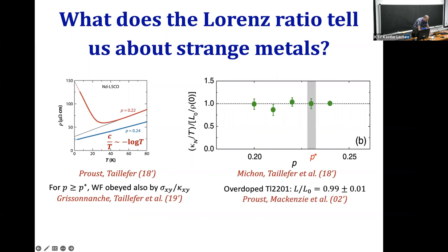Here's a different cuprate. Okay, so this is a thallium cuprate also that shows linear resistivity down to the lowest temperatures over a range of doping, actually, where superconductivity is suppressed by high field. And here the Lorenz ratio is obeyed up to 1%.